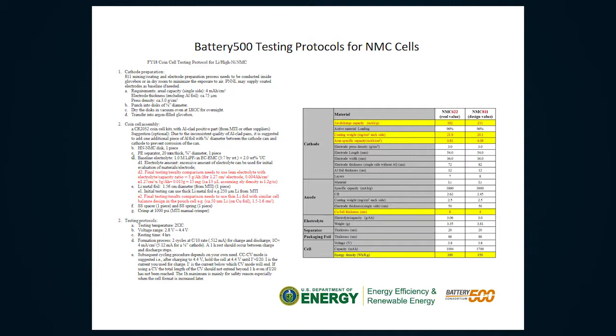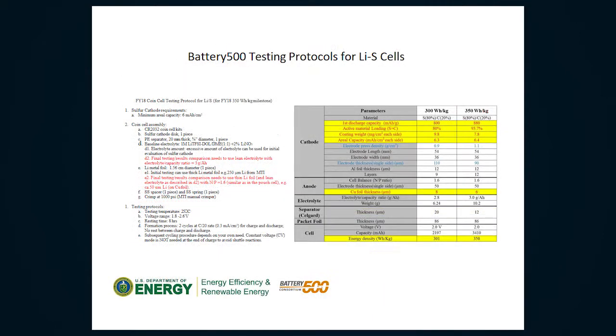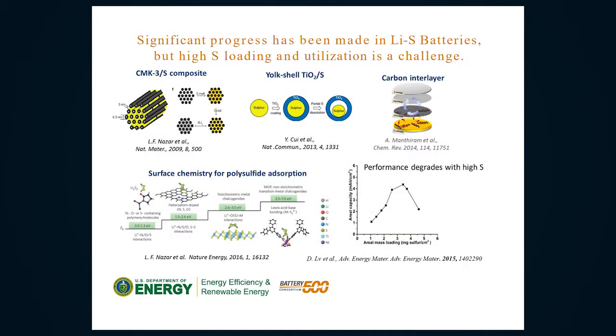So how much cathode and anode material you use, the amount of electrolyte, and including the separator, everything. If you don't do this, it doesn't really tell you anything about the real performance of the electrolyte material or the cell. We did something very similar for lithium sulfur. That's what I'm going to talk about in the rest of maybe 5 minutes or so.